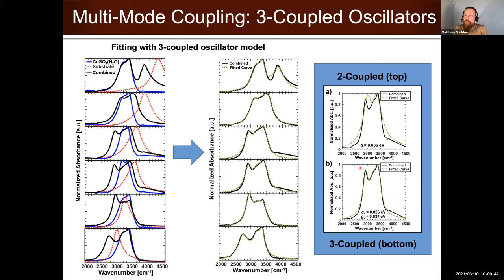And ultimately it was working with Matt Pelton at UMBC, who helped us derive an extension and work through the thinking of a three-coupled oscillator model, where basically we assume that both the symmetric and the anti-symmetric, or the asymmetric, water stretching mode can both couple simultaneously with the plasmonic substrate. And then it's really beautiful.